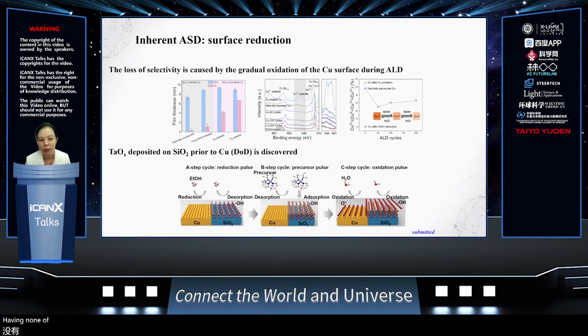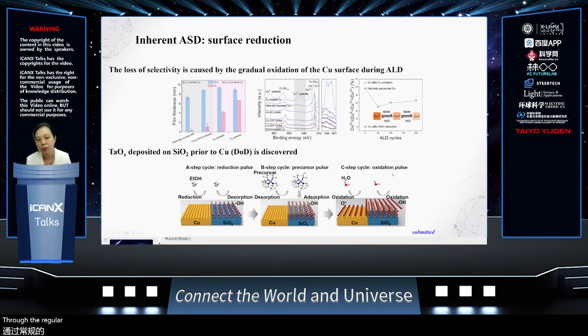Having known that, before the regular ALD, we actually added one extra step. We use ethanol to remove the surface absorbed oxide, or we dissolve this kind of naturally absorbed oxide, and then run this kind of ALD process. The good thing is that as long as you turn it into this kind of copper metal, and you choose the precursor very well, they start to be absorbed on the oxide only.